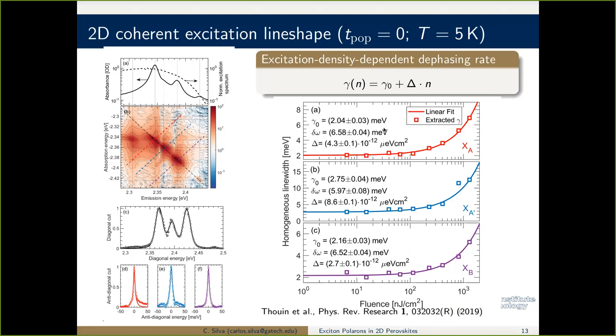This is the inhomogeneous line width. That's not very different. There is inhomogeneous broadening here as well, and that's what it is. But if we look at the density dependence of the dephasing, it's very different for exciton A, exciton B, and this intermediate species that now we see, what we call A prime. And this is measurably different. This is really quite clearly different.